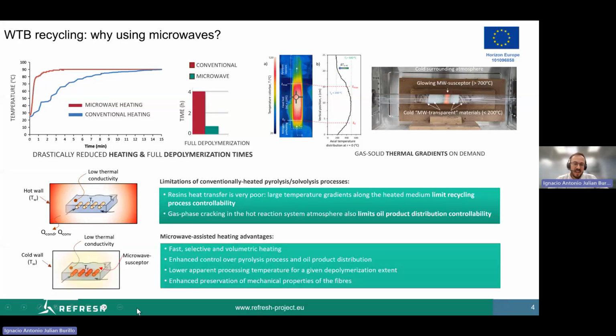Contrarily, microwave-assisted heating gives some advantages. As said, fast, selective, and volumetric heating that aim to control the pyrolysis process and the oil product distribution. Furthermore, we have realized that the apparent temperature of the process is significantly lower than under conventional heating, and that gives a better control on the mechanical properties of the resulting or reclaimed fibers, as well as of the oils.